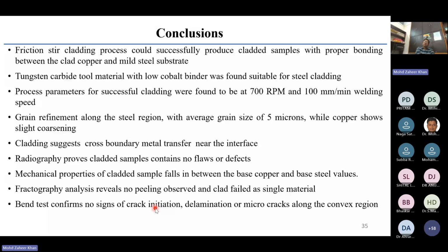Grain refinement along the steel region was seen with an average grain size of 5 microns, while copper showed slight coarsening. Cladding suggests cross-boundary metal transfer near the interface, but radiography proves that the cladding specimen does not contain any flaw or defect. Mechanical properties of the cladded sample fall in between that of the base copper and base steel. Fractography revealed no peeling was observed and the clad behaved as a single material, and the bend test confirmed no signs of crack initiation, delamination, or micro crack along the convex surface.